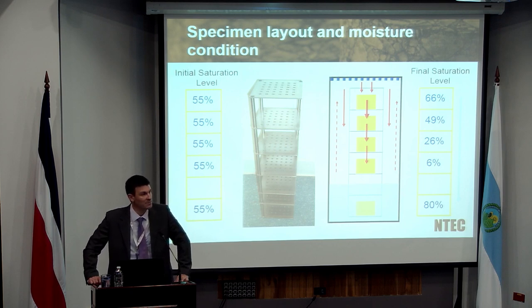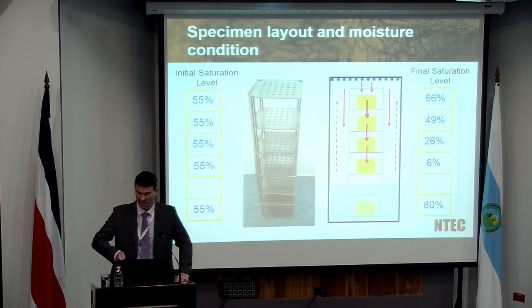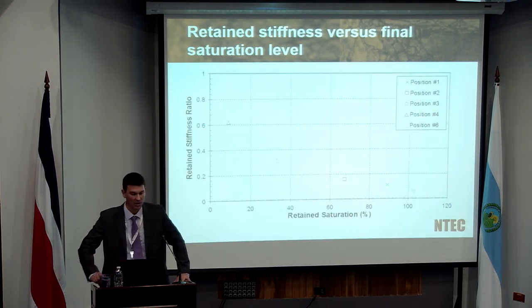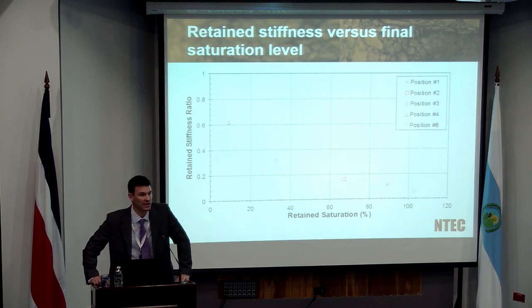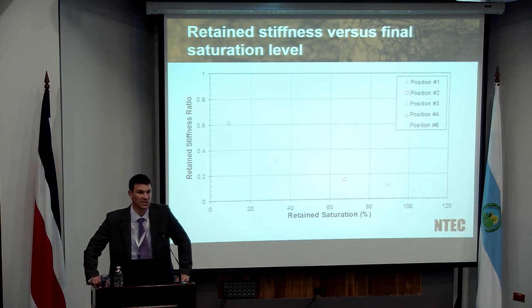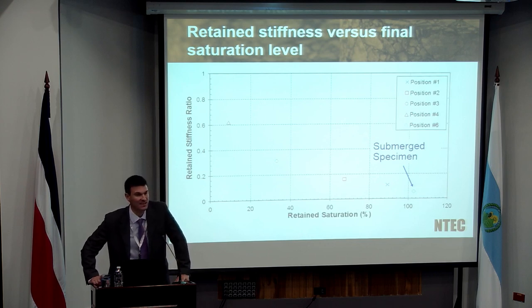But then you find your four specimens above your reservoir give you a whole range of different values. Some of them could be quite dry. This particular one at the bottom there gave us about 6% water content or 6% saturation. The one on the top about 66. You then do your testing, same kind of testing that we talked about before. We measure a dry stiffness before we do the conditioning and then a wet stiffness. You work out your retained stiffness ratio, and you now can plot the results as a function of the individual saturation in that specimen. And so obviously the submerged one in this particular case is just over 100%. There's obviously some error in terms of expansion of the specimen potentially, but say 100% saturation, and that would tend to give you the lowest value, but you end up with a range of different values.